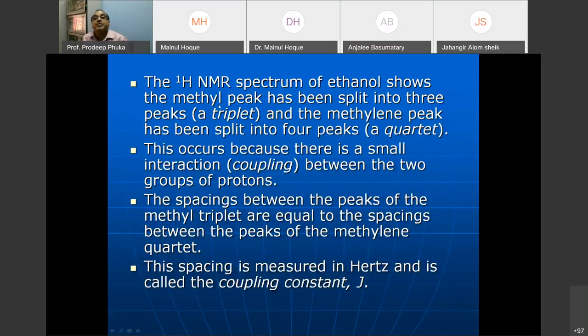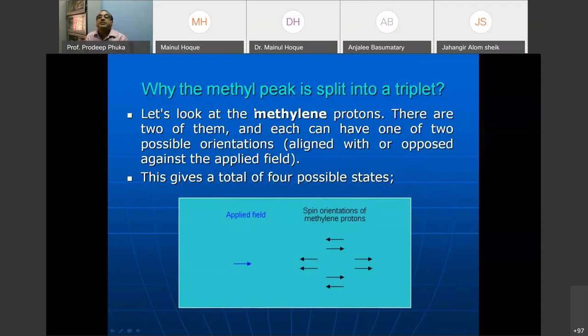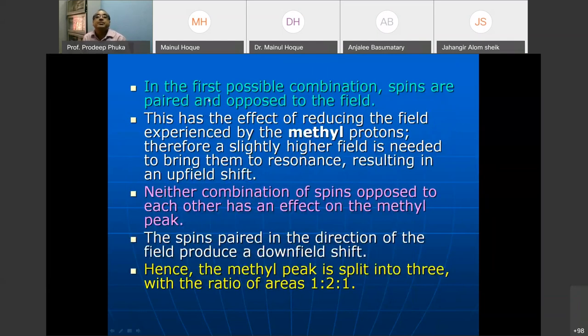The NMR spectrum of ethanol shows the methyl peak has been split into three peaks and the methylene peak split into four peaks. This occurs because there is a small interaction between the two groups of protons. We'll discuss this a little more here. You can see here, once you apply a field, the spins of the two different protons will either oppose the magnetic field or be aligned with it. In this case there are two orientations each, so four orientations in total, but two of these orientations have the same energy, so you will have one, two, one. So that is the reason why the methyl peak is split into three, with a ratio of areas 1:2:1.